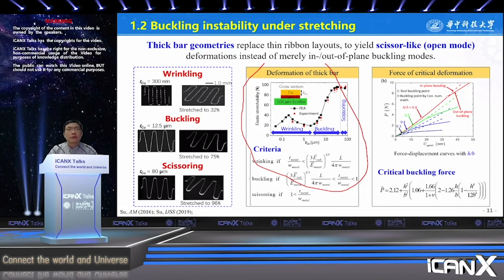The thinner the structure is, the easier the wrinkle is. And the thicker the structure is, the easier the scissoring is. The moderate thickness is easy for buckling behavior. The right figure shows the force-displacement curve with the ratio. With the increase in the thickness, the in-plane buckling suddenly changes to out-of-plane buckling. The two lines are the solid line and the dashed line. The unstable changing point for the structure with different thickness to width ratios is calculated theoretically.